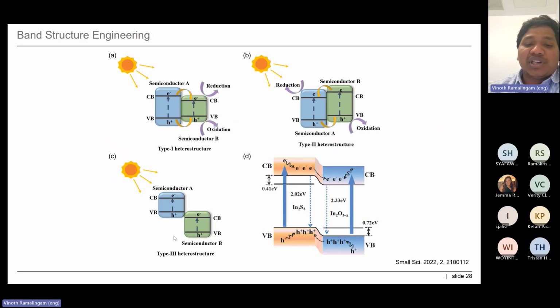The third one is the type 3 heterostructure, where you have two separate semiconductors. Each absorbs light and is involved in its own individual reaction process. This is an example of an indium sulfide and indium oxide based photoelectrode, where the electron moves from indium sulfide to indium oxide. The holes move in the opposite direction, from indium oxide to indium sulfide. Here the electron is involved in the water reduction reaction, and the holes are involved in the water oxidation reaction.